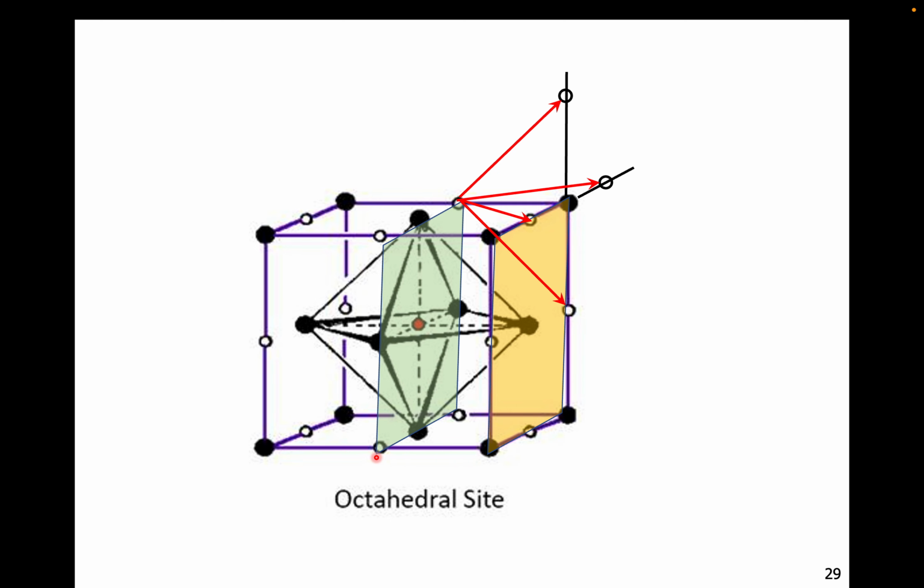The same idea, half, half, half, half, and usually it's symmetric. So usually the other side, you also have the other one. So I have the half, half, half, and half. So I also have 4. 1, 2, 3, 4. But this vector is parallel with this one, this vector parallel with this one. So even though this can make 4 possible jumping directions, these 4 are identical with these 4. So for the possible jumping directions, only 4.